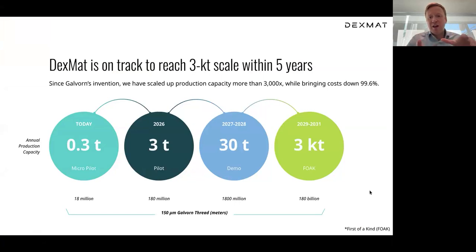Since we first started making Galvorn, we've increased our production capacity by a factor of 3000x while reducing costs by 99.6%. Today we're still at a relatively small annual production capacity of about 1/3 of a ton per year. However, because we have such a lightweight material, this translates to a significant length of conductive thread: about 18 million meters of thread, about 150 microns in diameter, from this 300 kilogram per year capacity. However, our goal is to produce Galvorn in large volumes and at very low costs to be on par with commodity materials like copper, aluminum, and steel.